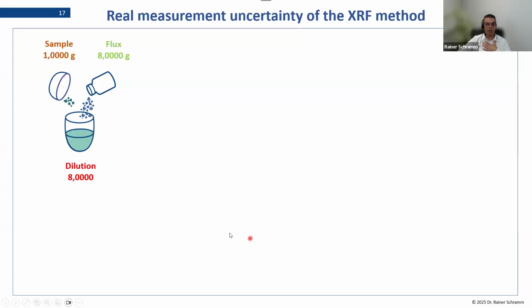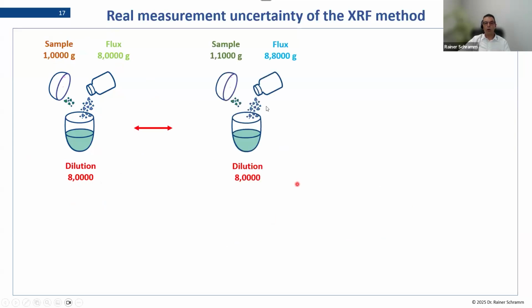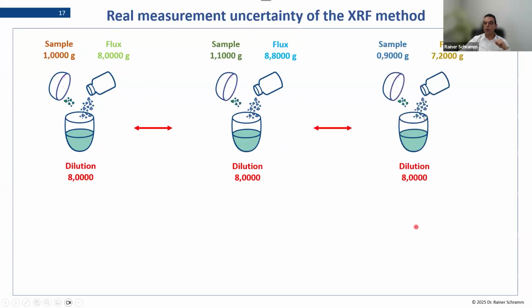So what is this? If you really want to do a fusion and you expect a dilution factor of 8, you weigh 1 gram sample and 8 gram flux, ideally. You could also weigh 10% more, 1.1 and 8.8. The dilution is still the same. And remember, it's the dilution that counts and not the absolute mass. Or you could do 10% less. That means you weigh 0.9 and 7.2 and still you have a dilution of 8.